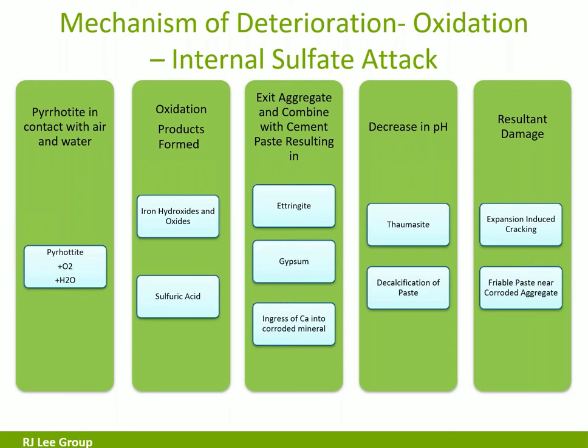I said previously, pyrite does not oxidize nearly as readily as pyrrhotite. Concrete or other cementitious matrix, such as stucco, further protects the mineral from oxidizing. Most of the pyrite issues occur when a grain is at or just below the surface. So this is commonly seen just as staining. Sometimes it'll progress to pop-outs or cracks.